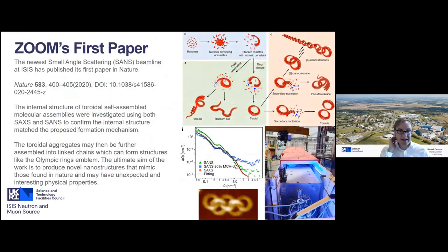We can also study soft matter as well. This is a recent example from ZOOM, one of our latest instruments, a small angle instrument, which is work with colleagues in Diamond, in Japan, Switzerland, Italy, so huge collaborations, in this case, creating these interlocking structures that you can engineer their properties. And the really amazing thing here is that you can organize these structures in a self-assembly so that they start to interlock, which is really difficult to do. So you have to have these kind of pre-annular molecules that then pre-organize and that then give you these little structures. Now, I do wonder if the reason this is in Nature is because we have the Olympic rings here in what turns out to be an Olympic year.